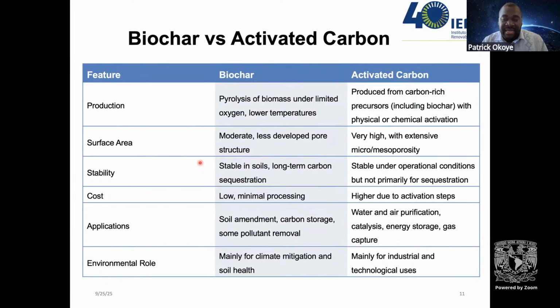Then the surface area of biochar is considerably lower compared to that of activated carbon, because activated carbon has well-developed micropores. And these micropores and even the pore volume translate to the surface area. If you apply some model, which we are not going to talk about today because of how extensive that is, you will see that you can calculate the surface area. And obviously biochar, because it is obtained at a lower temperature and there is no activation at all, does have less developed pore structure and lower surface area.